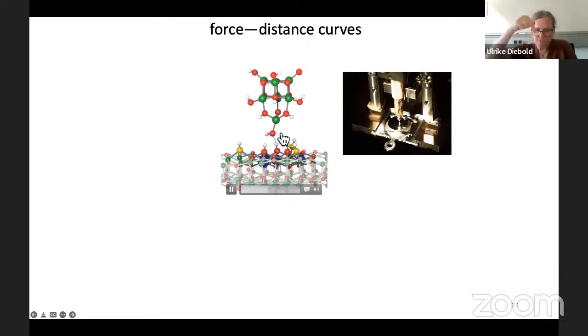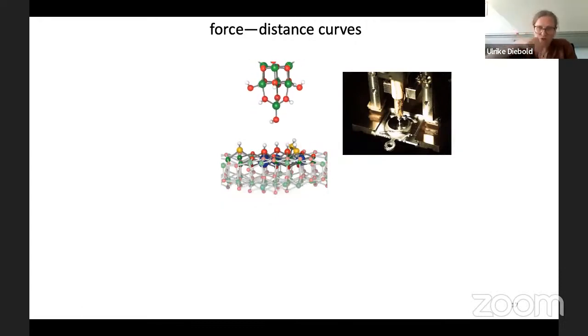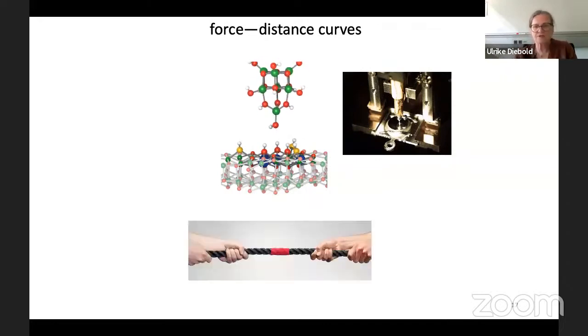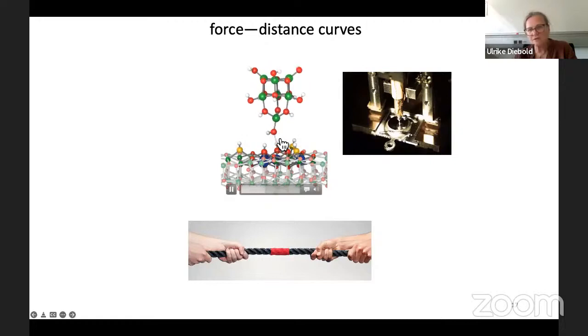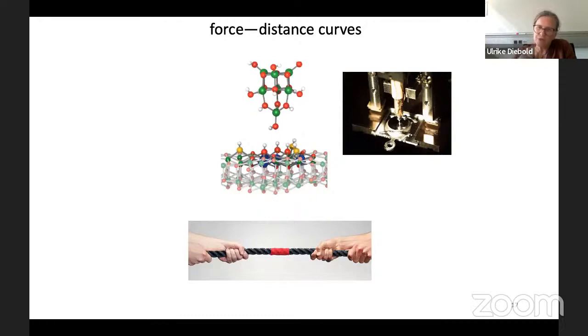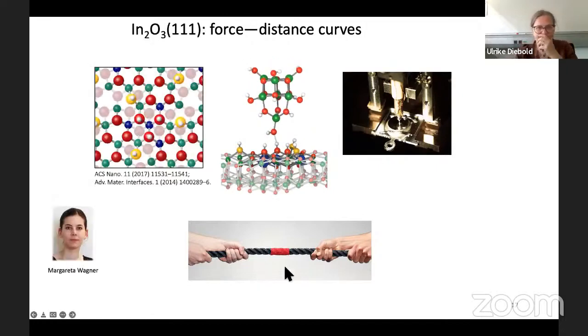So what we do is we have these wonderful atomic resolution images of a well-prepared surface with hydroxyls. We bring the tip closer, so we park on top of the surface, we go in and out and measure these force distance curves. That's what we do on single atoms. You can think of it like this: we have this hydroxyl here and the tip goes close enough that it forms a hydrogen bond with an OH group. And then the tip and the hydroxyl on the surface compete for this proton, like in a tug of war. And I will show today some results by Margareta Wagner, who's a postdoc in our group.